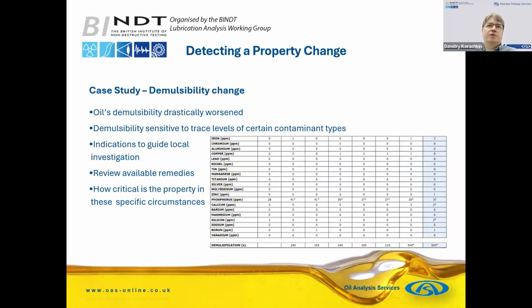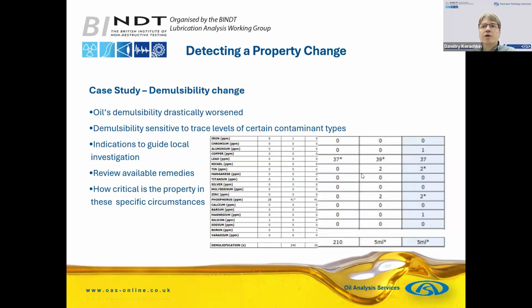But it's not just about finding out what the contamination is, it's also finding out what you can do to deal with it. And in this situation, whether this property is critical or not, because the demulsibility is important when there is water getting in, but if you have very good controls of moisture levels, no water getting in, you may be able to continue with this condition where the demulsibility is not ideal. So we saw, as I said, a little bit of calcium and a little bit of silicon, which initially did not strike us as particularly high and abnormal, but once the problem was confirmed, we investigated further, and that was a possible cause for the demulsibility problems.